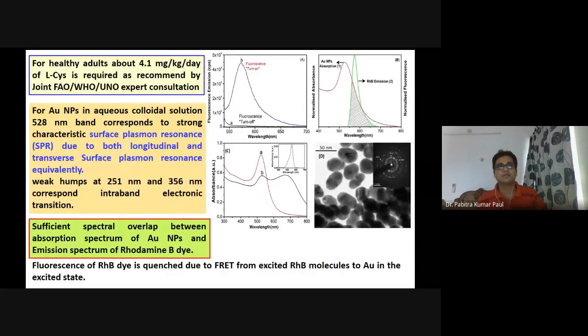Gold nanoparticles in aqueous colloidal solution have a band at 528 nanometer, which corresponds to the strong characteristic surface plasmon band for both longitudinal and transverse surface plasmon resonance. There are also two weak humps, at 251 and 356, which you see in this picture and which correspond to intra-band electronic transitions. From this picture, you see that there is a sufficient spectral overlap between the two. The gold nanoparticles are the acceptor, and the absorption spectra of gold nanoparticles and the emission spectra of rhodamine B have a large spectral overlap.